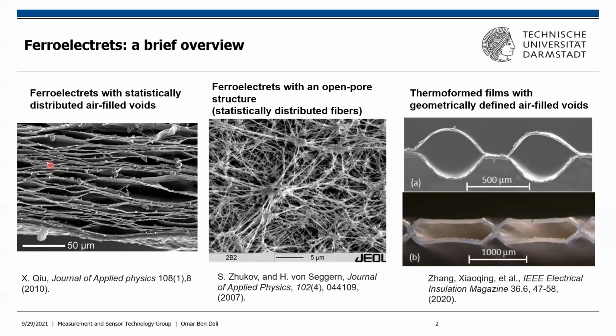The first one, as you can see here, is ferroelectrets with statistically distributed air-filled voids. In this class, cellular polypropylene features an outstanding quasi-static d33 coefficient of up to 300 picocoulomb per Newton. The next class is ferroelectrets with an open pore structure or statistically distributed fibers. This class is based exclusively on expanded PTFE and exhibits a remarkable piezoelectric d33 coefficient of up to 1,600 picocoulomb per Newton.